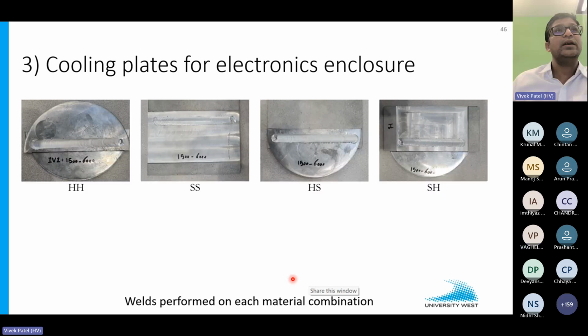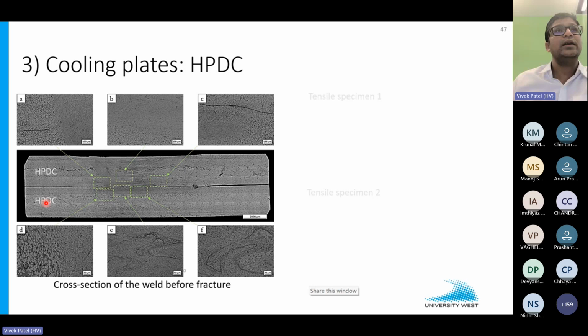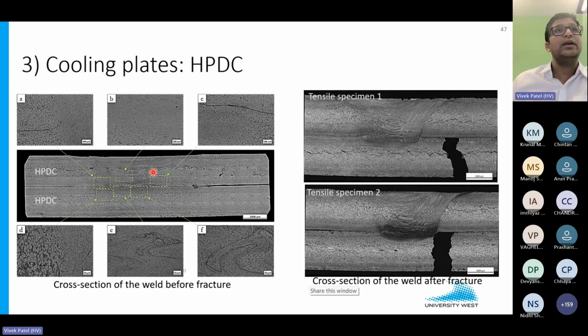So some of the process parameters I can show you. This is the high pressure die casting, top, bottom, same material. And this is a cross section. And when we test in tensile, and then observe the cross section after tensile, you see the failure happens from the parent material rather than the weld nugget. So the weld nugget is intact.